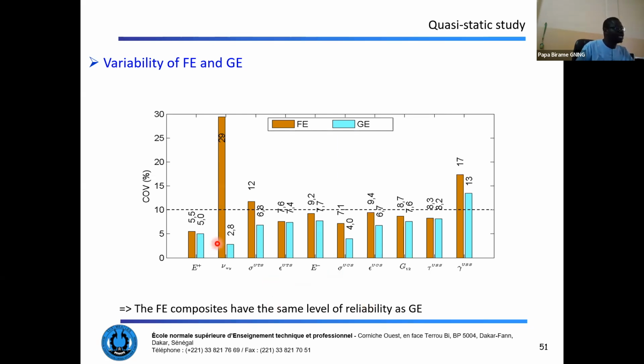So when we compare now the properties of the Flax epoxy to the glass epoxy composites, we see that the Flax epoxy are brown here, the glass epoxy are plotted in blue bars. We can see an overall average value lower than 10%. So what does it mean? That means that the level of reliability of the Flax epoxy composite is comparable to the one we have for glass epoxy composites, even if elementary glass fibers have a coefficient of variation of around 13%, as we have seen.